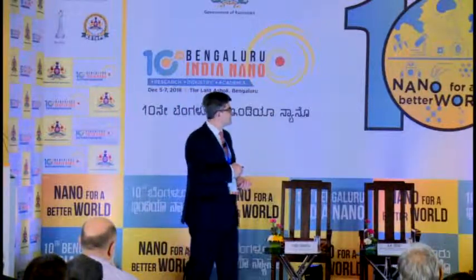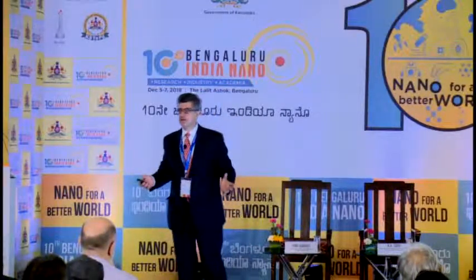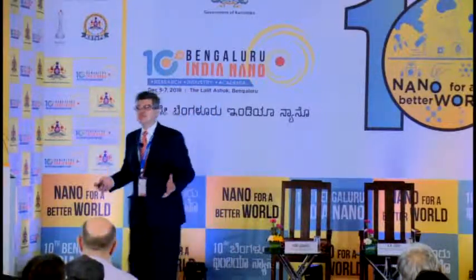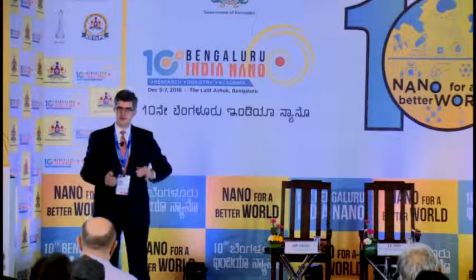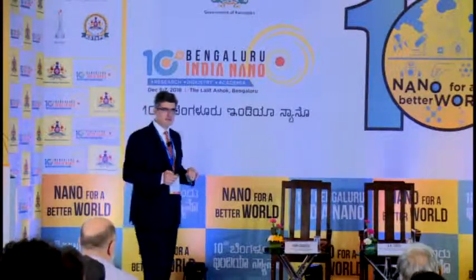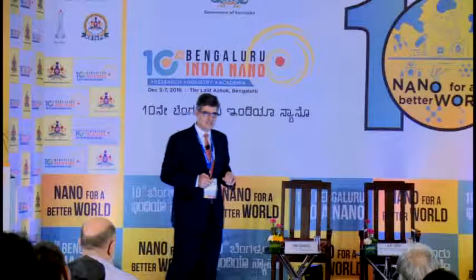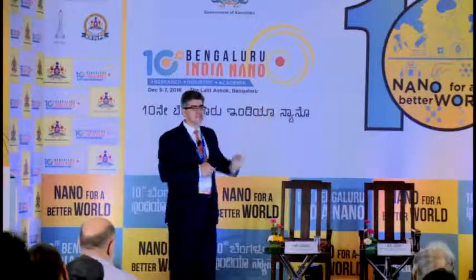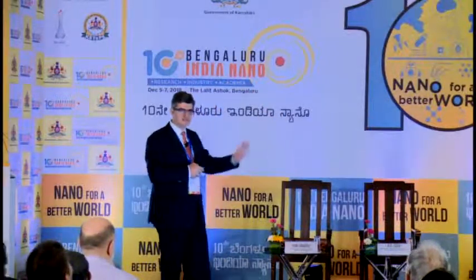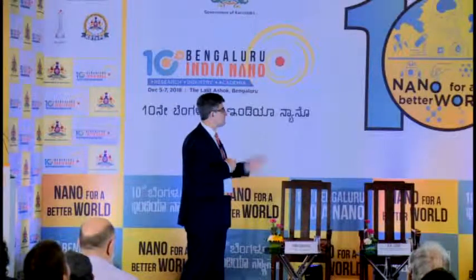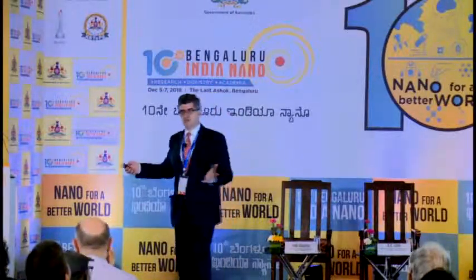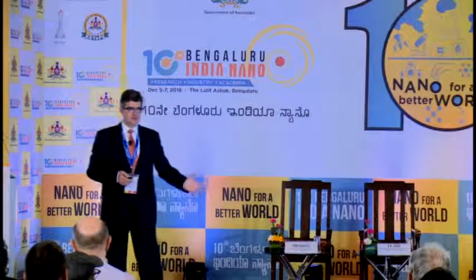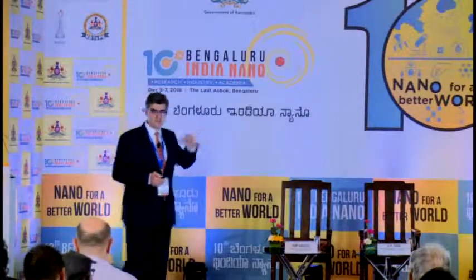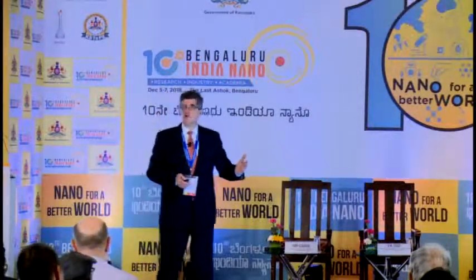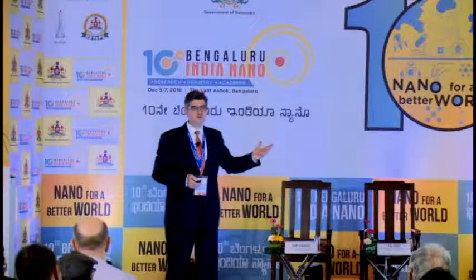You can see the Tyndall effect, but if you dilute solutions of different MXenes, you will get different colors because they have different electronic properties. Some of them are actually semiconductors or narrow band gap semiconductors or semi-metals, but there you see they give plasmon resonance at different wavelengths. They're different here. But when you have a colloidal solution, it doesn't matter, you have graphene oxide, you have boron nitride, something else. Important is that since they have hydrophilic oxide-like surfaces, we can work in water.